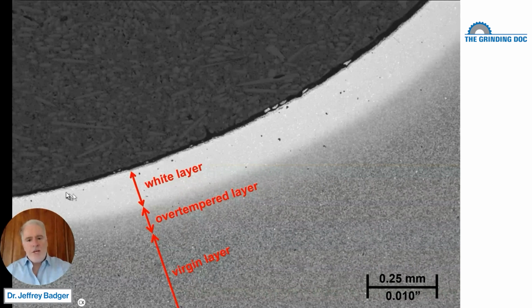So what we have here is a ground surface right here. This is just the mounting material that you see. This is the ground surface, and what's happened is for a layer of about 0.2 millimeters, that top surface has passed the austenitizing temperature and is recrystallized.